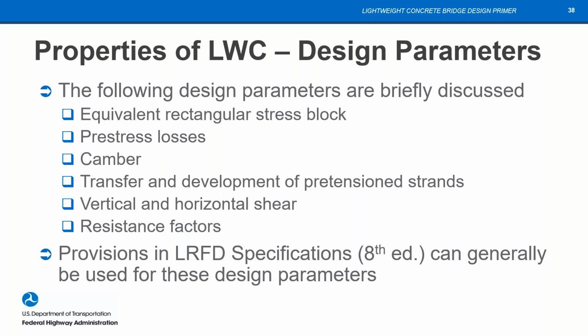One thing that we oftentimes think about or discuss with lightweight concrete: are the pre-stress losses different? Well, what some of the testing has shown is, yes, the elastic shortening is greater because you have a reduced modulus, but there's not a significant difference between the creep and the shrinkage. We just saw that it could even be less for lightweight concrete. So we can use the equations that are in the specifications. Camber will typically be greater because you have less dead load and a lower modulus. So the camber typically can be more. We may be able to mitigate that in our designs if we choose to. But otherwise, we use the requirements in the LRFD specs for our design without any problem.